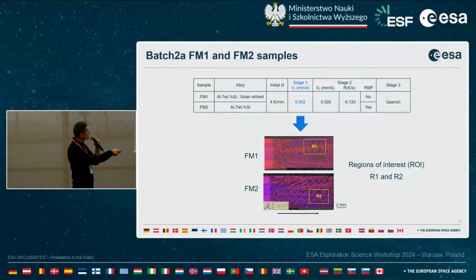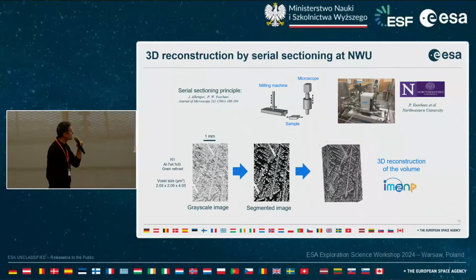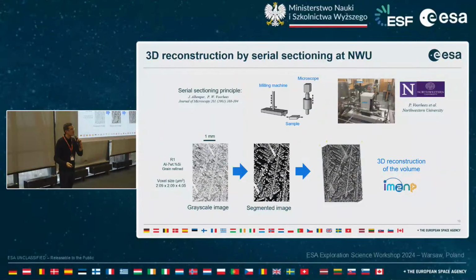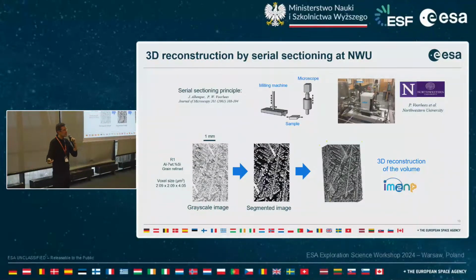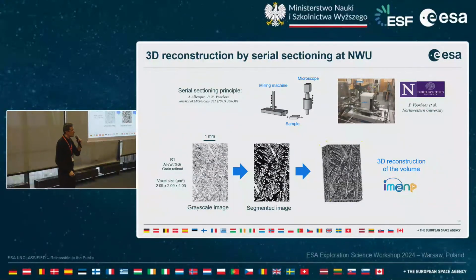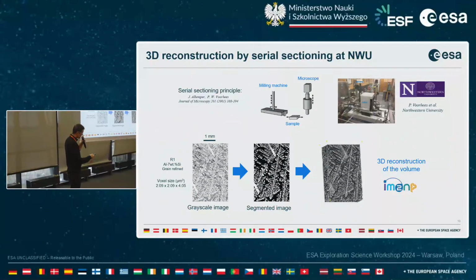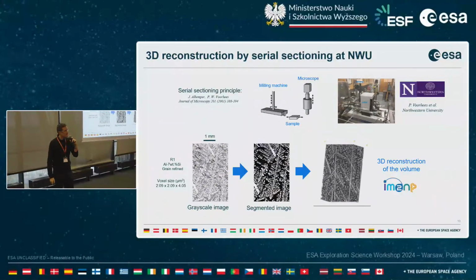And we studied these two regions in detail using a not so common technique, which is serial sectioning. So we selected these regions, and we sent the samples to Peter Voorhees' group at Northwestern University in Evanston, USA. And they did this serial sectioning investigation, which consists in taking a sample to a milling machine. You remove one layer, then you take a picture at a microscope, and you go back to the milling machine, you remove another layer, you take a picture, and by stacking all the images, you can retrieve a stack of grayscale images, and after some image processing, the idea is to obtain a 3D reconstruction of the volume. So this is what we got from this technique.